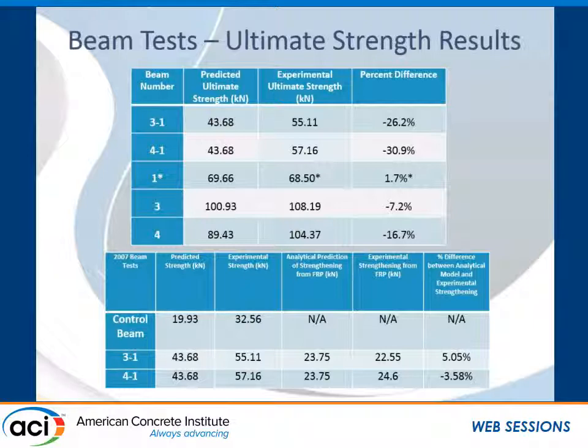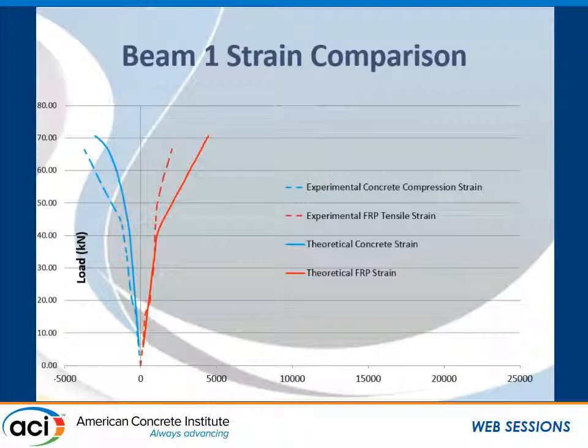So we took a look at these beams in the percentage of strengthening that was achieved. And here we see agreement between the analytical model and experimental results much closer, suggesting that the proposed methodology accurately predicts our strengthening effects. We also looked at strain in the concrete and the FRP from strain gauge data, and you see the comparison for beam 1 from 2007 over the range of loads here.